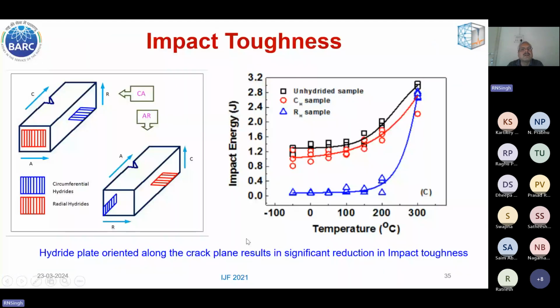Here we show the effect of orientation. So these red lines and blue lines show the hydrides. So we considered here 8 permutations and combinations of hydride platelet orientation with respect to crack plane. And the summary is that if hydride platelet is oriented parallel to the crack plane, there is drastic reduction in fracture toughness or impact toughness, especially at lower temperature. As you go to higher temperature, toughness improves. However, if hydride platelet is oriented normal to the crack plane, toughness is not that much reduced.